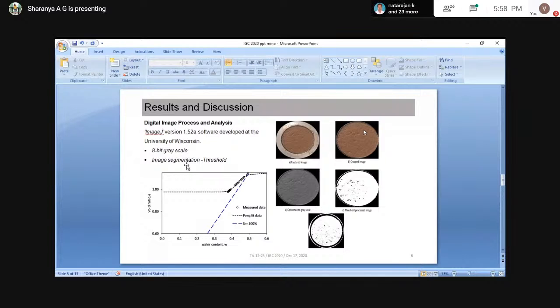This threshold limit plays a major role in the reliability of this image analysis process. By performing this process on soil samples, I determined the volume, and the volume was converted into the void ratio, and the shrinkage curve plot was obtained for my soil sample. The same experimental data was fitted into the mathematical models I mentioned earlier. This is the soil shrinkage curve I have obtained, and from the curve, not all soils possess all four shrinkage zones. This soil possesses only the proportional or normal shrinkage zone, as well as the residual and zero shrinkage zones. This soil lacks the structural shrinkage phase. So this gives an overall idea about the pore size distribution of this soil.